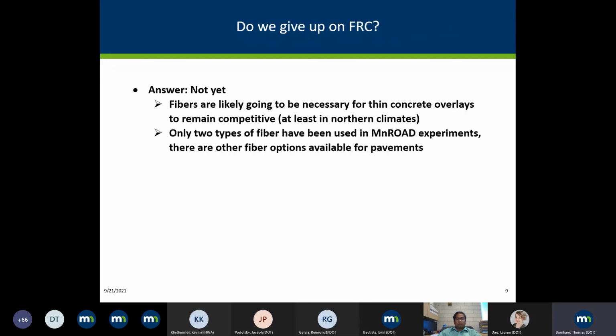So the question is, we've been at this for 20+ years. Do we give up? I say no, not quite yet. Because at least in our climate, from what I'm seeing, I think fibers are going to have to be necessary for these thin concrete overlays to remain competitive. Because if we develop faulting very early on, that's an extra expense over and above the initial cost. So my hope is that we do find a fiber that will serve the purpose of mitigating the development of joint faulting. And again, we've only used 2 types of fibers in Minroad experiments. There are other fibers out there that we have not had the opportunity to try, and perhaps they might work better than the ones we did.